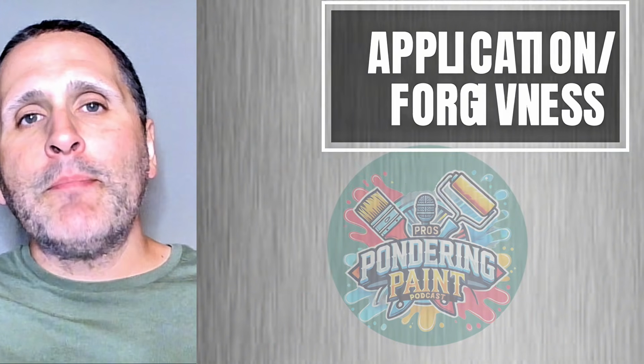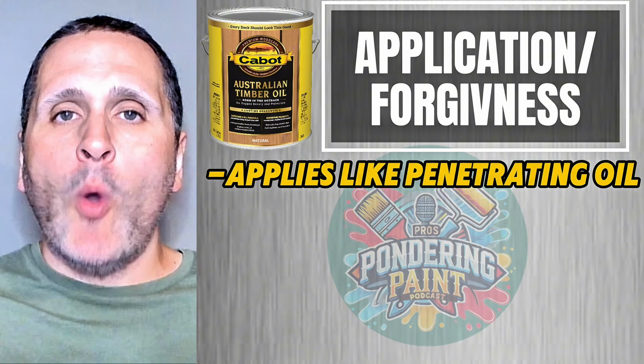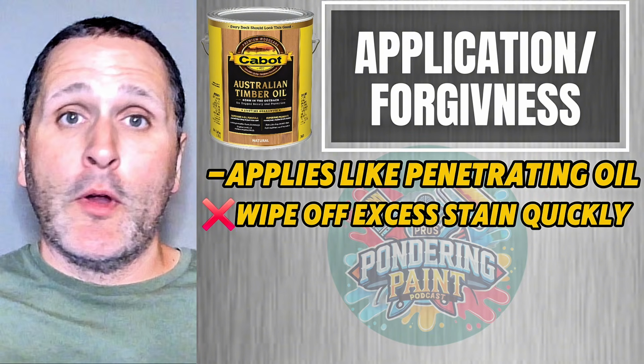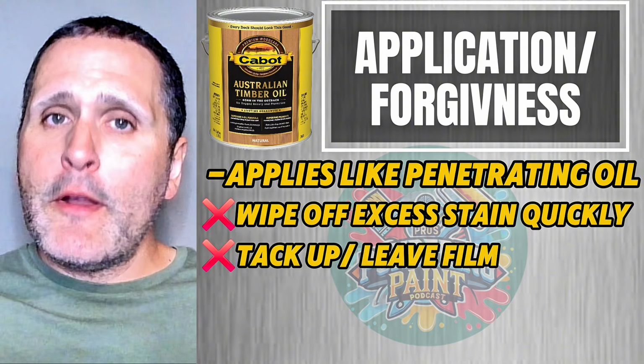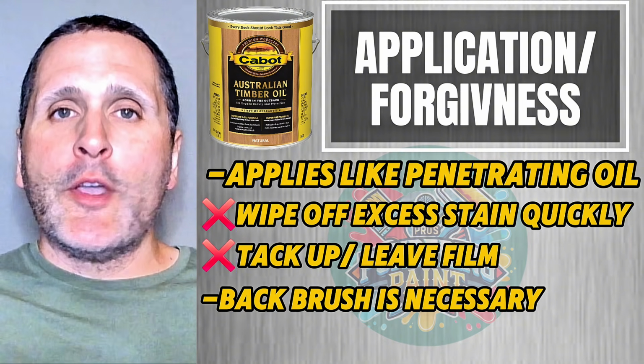Let's consider application and forgiveness. Cabot applies like a penetrating oil. That means that you need to make sure you wipe off any excess within 30 to 60 minutes of applying. If you don't do this, it could tack up and leave a weird film on the surface. And because of this, back brushing is absolutely critical.